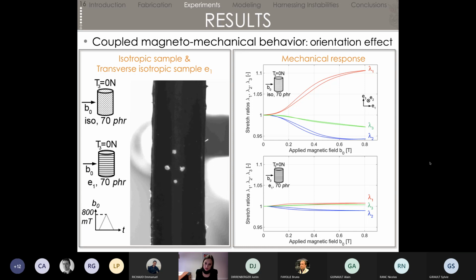The curve at the bottom corresponds to the sample for which the chains are already aligned with the magnetic field. We measure really, really small strains here. And in fact, we think that if we were able to cure the sample within its mold, remove the mold and right away proceed to the test, we would not see any strains. So for us, it's just residual strains due to the fact that the sample is not exactly in the same position as the position in which it was cured. Essentially, the particles are already in their optimal configuration with respect to the magnetic field, so they don't need to move anymore. That's why we do not measure any sizable magnetostriction with these samples.